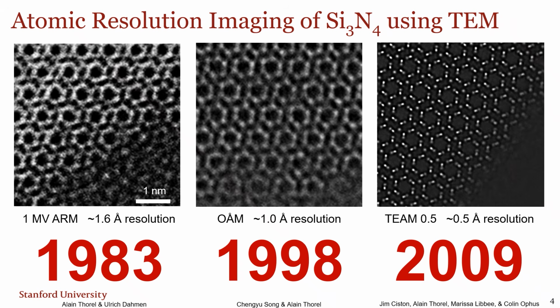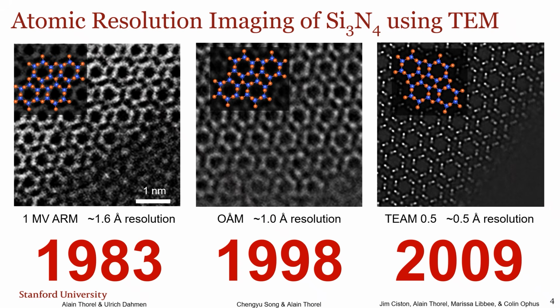And if I zoom in, you can see the importance of resolution. Even these small improvements, a factor 2, factor 1.6, you can now go from this hexagonal ring of blobs to separating those into the brighter silicon and the dimmer nitrogen here. So if I overlay the atomic structure, you can see the previous generation of microscopes was giving us lattice resolution, but now we're down to the single atom level here.